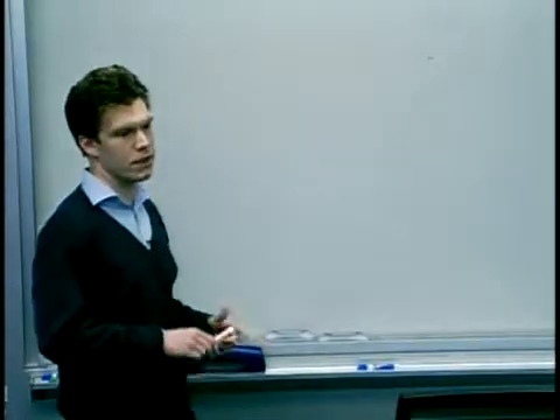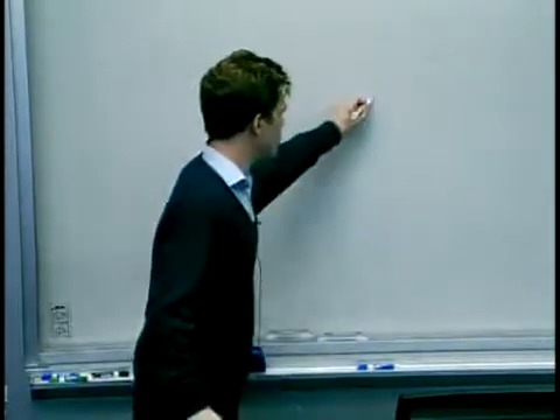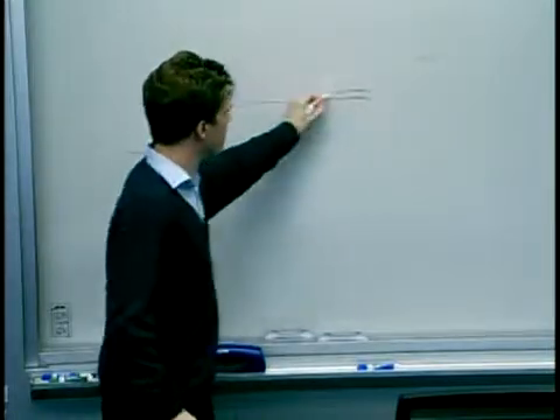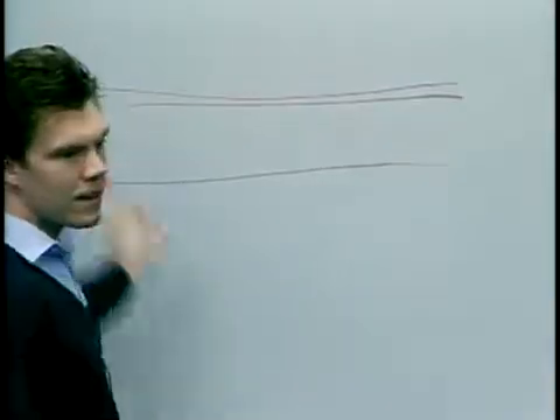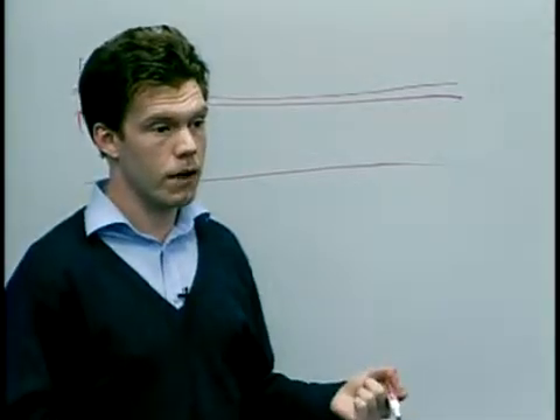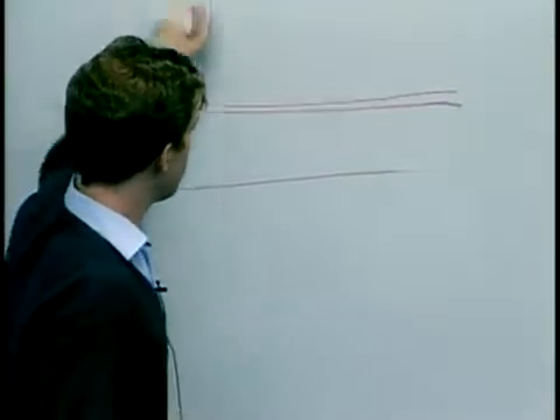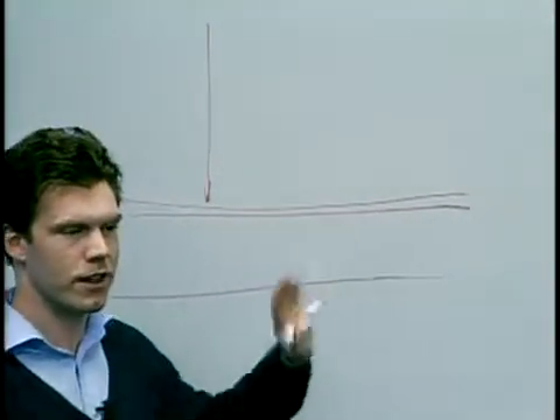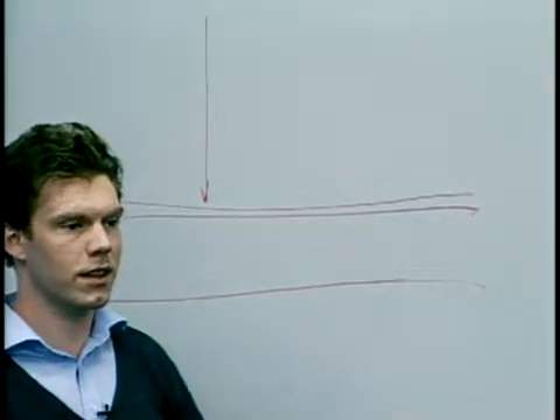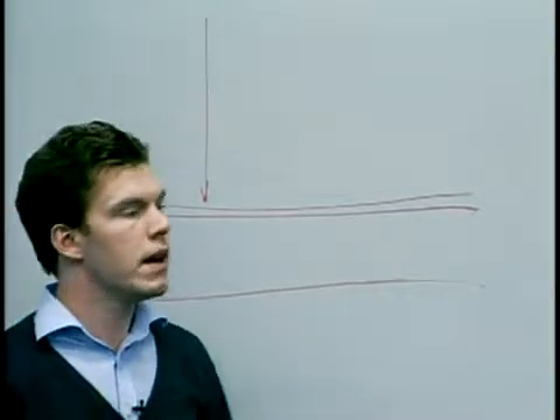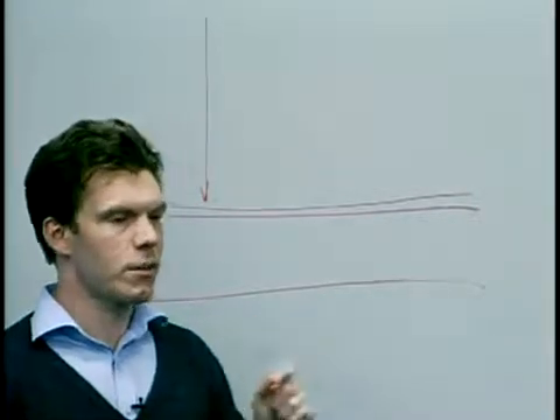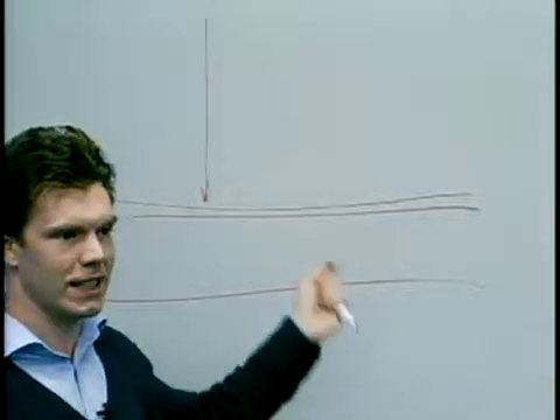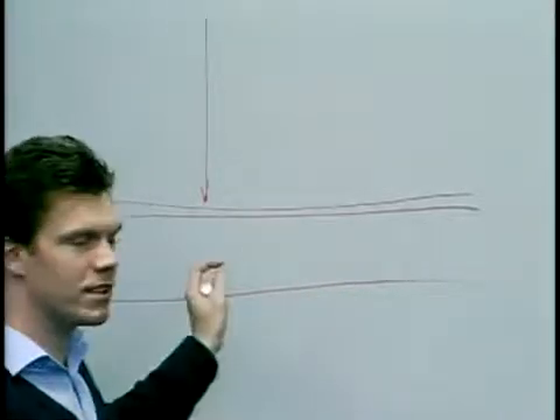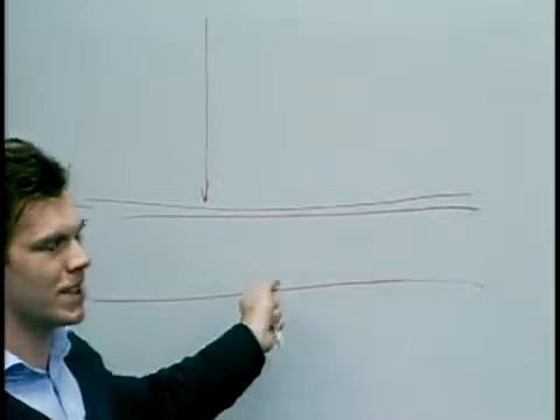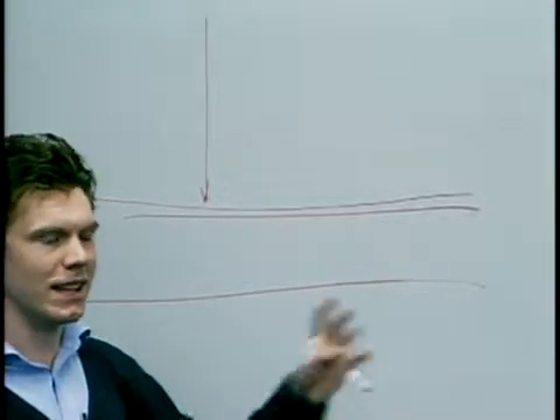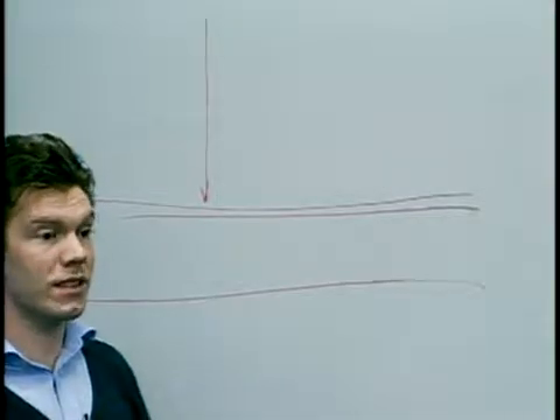electron beam lithography is a great candidate for that, where you would start with a silicon wafer with a 100 nanometer thick layer of a radiation sensitive resist. Then you would steer a focused electron beam across the surface, scan it across the surface in the pattern that you wanted. And that will give you 5 nanometer resolution or better. The trouble is it takes ages because it's a serial process. You're scanning the electrons over the surface. So once you've made the stamp, you've paid however many $1,000 for the stamp, you can stamp it in a minute into as many substrates as you like. And that's really the reason for nano imprint.